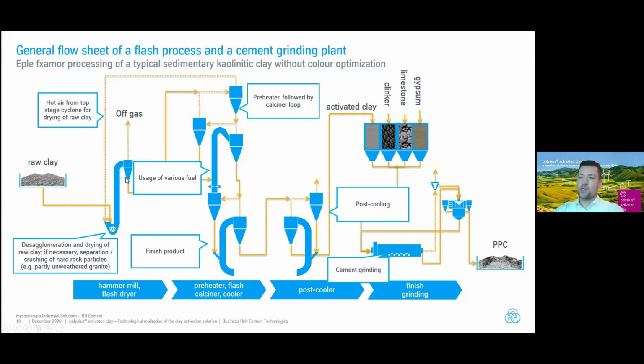And directly attached, we are bringing then the material to the preheater, where the material is preheated to a temperature of around 500 or 600 degrees C before entering the activator unit. So the activation is then done in this activator unit at a certain temperature between, let's say, 800, 900 degrees C, depending on the clay. And then the material stream is separated in the product cyclone. Afterwards, the material stream is guided into post-coolers to recuperate the heat from the material and to reuse the heat in the system. So this is bringing the Opex quite low here.